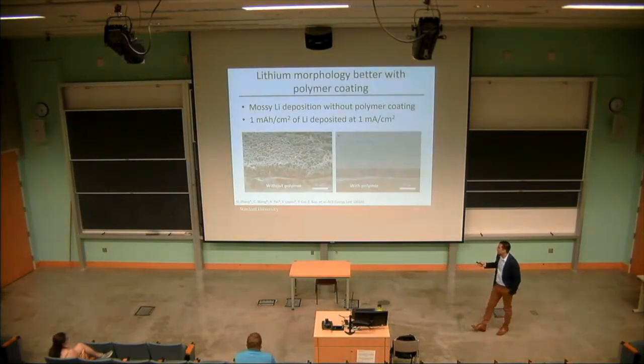So when we look at cross-sectional SEMs of lithium deposited on copper without the polymer, you can see, as I mentioned before, these mossy or kind of loose lithium structures that form. But when we have the polymer coating, again, this is copper and then the lithium, we see very, very dense lithium deposits. And this is actually very close to the theoretical 5 microns thickness that you would achieve for 1 milliamp hour per centimeter squared of lithium deposited.